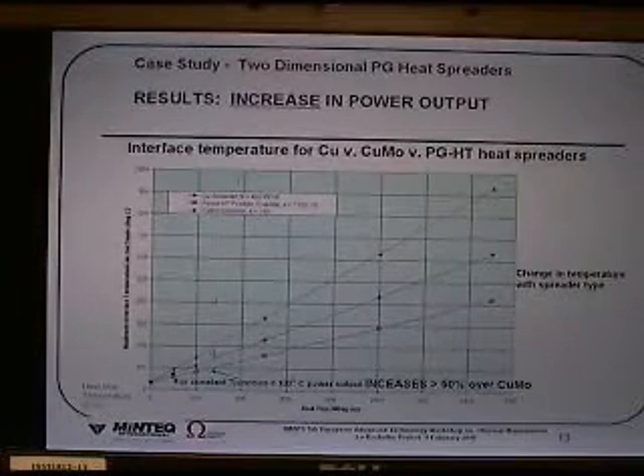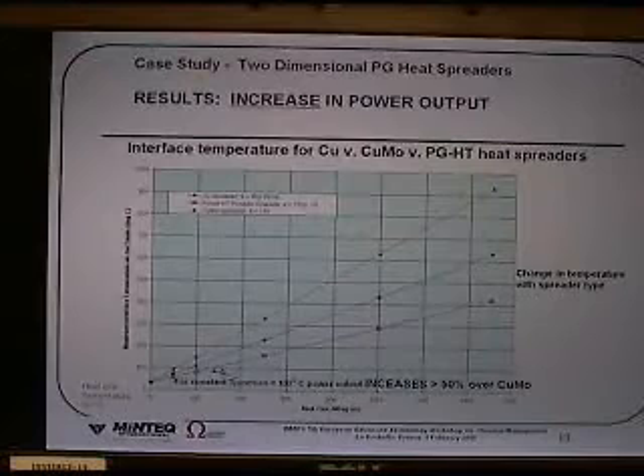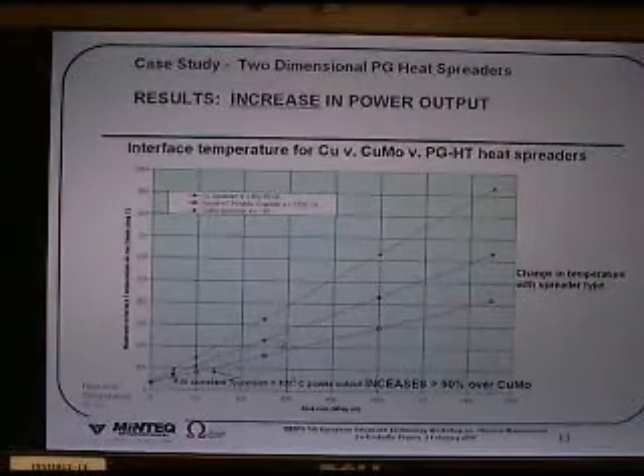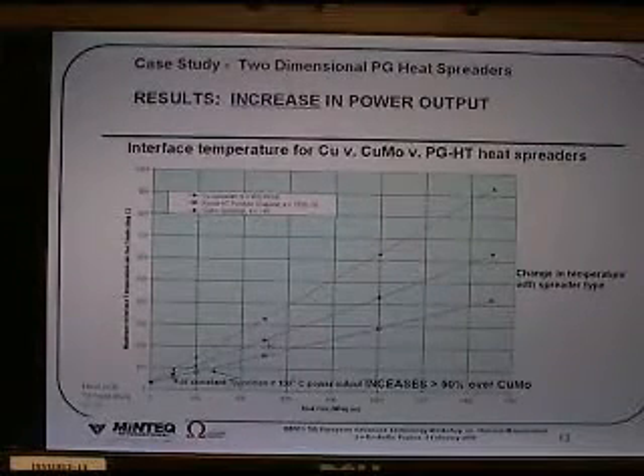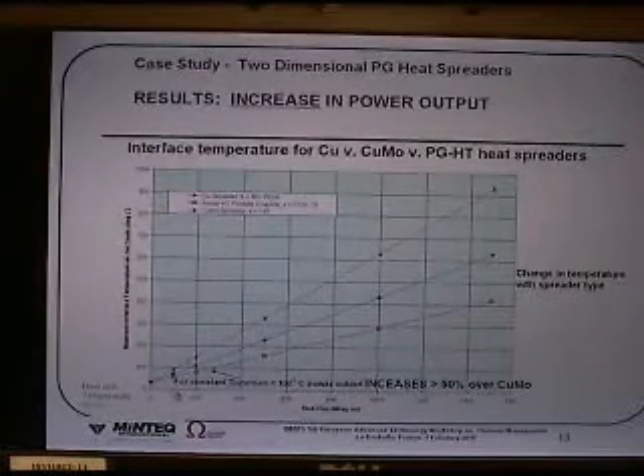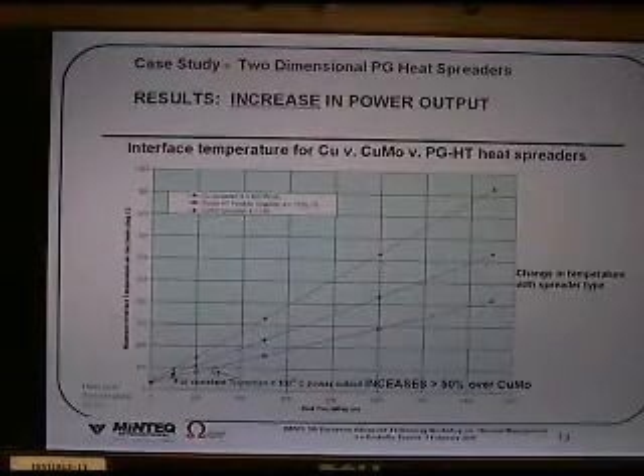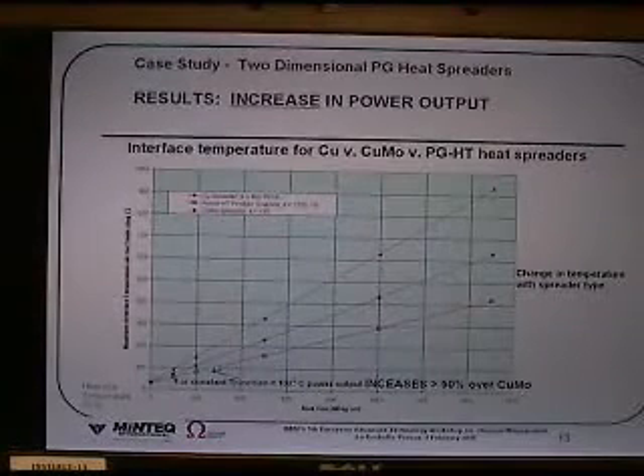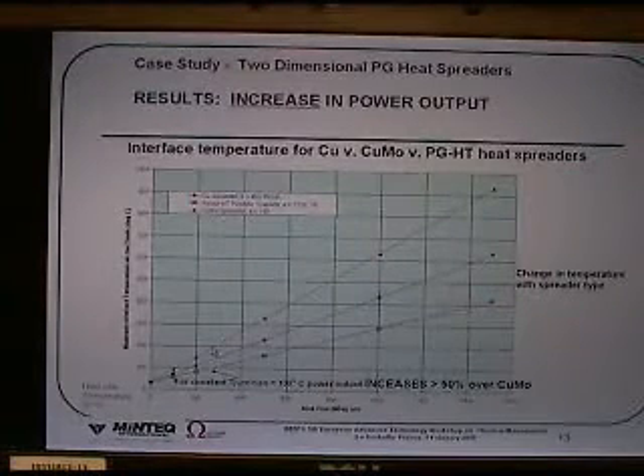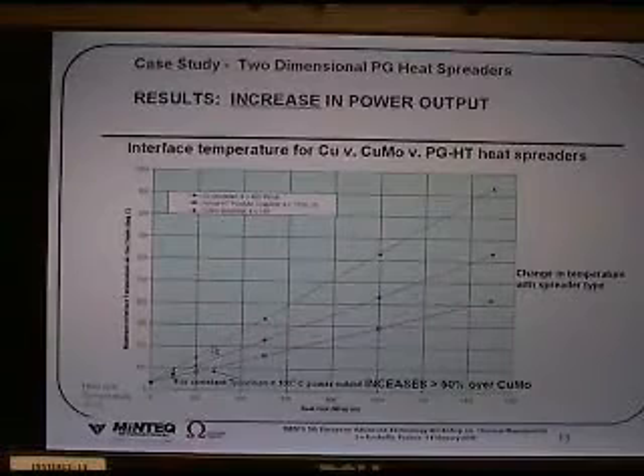Those degrees of freedom are illustrated in this graph, where we compare the results for the Pyroid HT, for a copper molybdenum, and for a copper heat spreader arrangement. And this indicates that for a constant junction temperature, for example 100 degrees C, we're able to increase the power output by over 90% compared to traditional materials. So we believe that Pyroid HT pyrolytic graphite offers a degree of freedom for the thermal management designer that did not exist before.